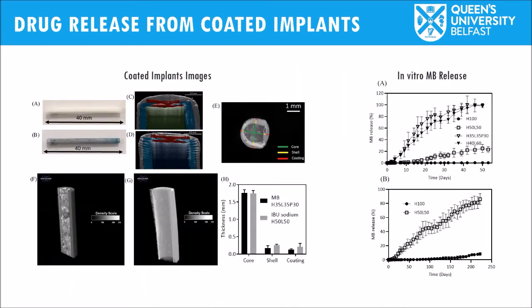The implants were coated with these formulations and characterized. Here you can see some cross sections of the coated implants, some pictures of these implants, and some OCT images highlighting the different sections. The coating is in white, the PLA casing of the implant in blue, the PVA window in red, and the drug core in different colors, here blue and green.